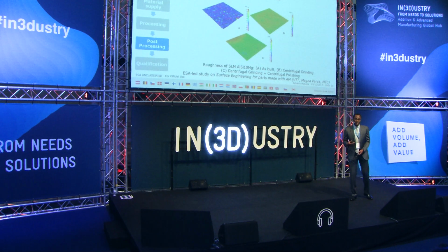After processing, you have the post-processing, so you need to clean your part to improve the surface. We have different studies in this field. This is a picture from one of our studies where we use different post-processing techniques on the surface, grinding, shot peening, polishing, in order to achieve the roughness that we need for our applications.